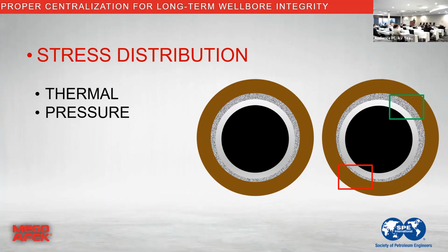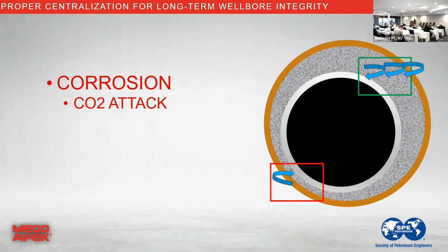The thinner the sheath, the more prone to acid attack, CO2 corrosion, CO2 attack, whether it's carbonic acid or supercritical CO2. And of course, as your tubulars expand and contract because of the effect of thermal induction, it's also going to fail or want to fail on the thinner side, which is, if I may, the path of least resistance for damage as well. So when it comes to CO2 attack, regardless of the slurry design, again, you may have the best slurry design, and we saw a couple interesting presentations regarding slurry designs. Still, the distance from your wellbore to the tubular is shorter on the shorter side. So it's going to corrode faster on that side.